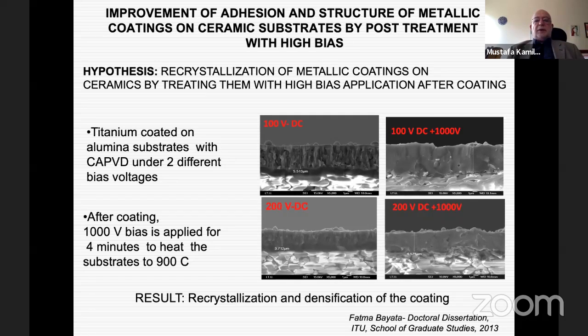The first study that we have conducted is that when you try to deposit these coatings on ceramic materials, the adherence of the ceramics to the metals is not very good. So you have to heat the substrate to very high temperatures. And also you have to make the surfaces rough, etc. And the additional thing is that we looked for very dense coatings that we want to produce on these non-conductive substrates. The idea was to deposit titanium metal on alumina substrates so that these titanium films will be further processed for sensor applications by using a porous anodic oxidation.